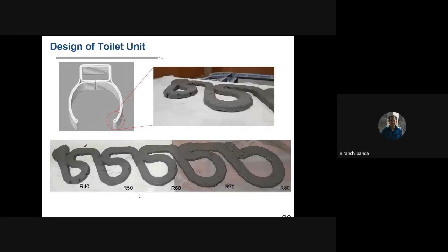So now keeping the same structure, if I want to avoid this kind of tearing effect, what do I have to do? I have to make the material slightly more soft, because it happened because the material is very stiff. So when you take a sharp turn, it is going to have a tearing impact. Now if I make the material slightly soft, I can go with a slow speed. This effect can be minimized. That is one possible way.